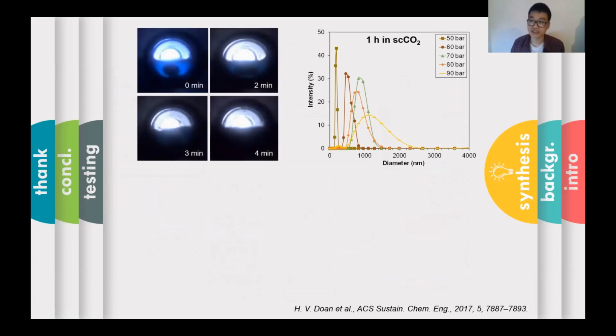We also found some interesting results for MOF synthesized by these methods. First, we can see that the supercritical CO2 can induce rapid nucleation after a few minutes. This is much faster than the 12 or 20 hours in reported synthetic methods. Also, increasing CO2 pressure can help to increase the average particle size. This suggests more rapid nucleation at higher pressure, which is similar to when we add a large amount of solvent. These results demonstrate that the particle size and dispersity can easily be controlled by varying the CO2 pressure.